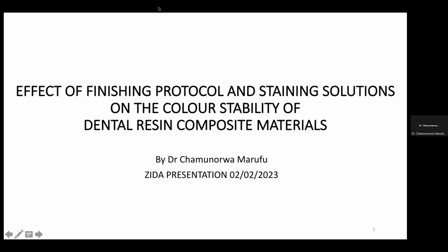You would note the resins which are usually used in most of these are BisGMA and maybe urethane dimethacrylate, and these are heavy molecules. They have a high molecular weight, so they are quite viscous. So in order to increase the filler loading, the manufacturers would add resins with a lower molecular weight like triethylene glycol-dimethacrylate. And unfortunately, this particular monomer has hydrophilic groups on it. So the other heavier chains are hydrophobic. So it is these monomers which are hydrophilic, which now encourage absorption of these stains into the restorative material.